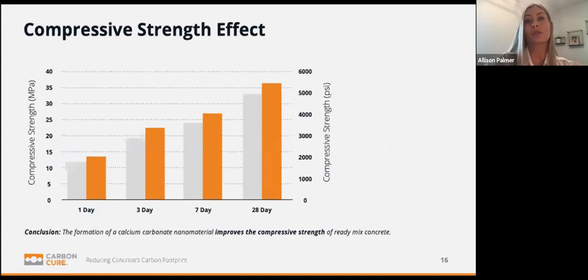Here we have an industrial trial average conducted over a number of studies. The two different bars are two different mix designs measured for strength for different dates after pouring. The lighter bar on the left is a typical concrete mix: sand, aggregate, water, cement. The orange bar is that same exact mix, but with CO2 mineralization.